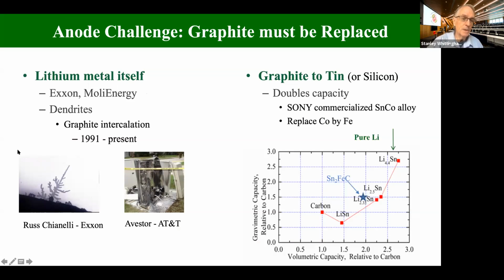In any metal deposition process, you tend to get dendrites formed. And this was work of Russ Chianelli, who's now, as I mentioned, in El Paso, at the University of Texas there. And this was one of the first operando studies in an operating battery. As soon as you get a little protuberance like this, then the electric field between this tip and the other electrode is increased. So once they start, they grow fast. And this will grow through any separator, even if it's a polymer, or even through the grain boundaries of ceramics. So there's a big issue on these dendrites.